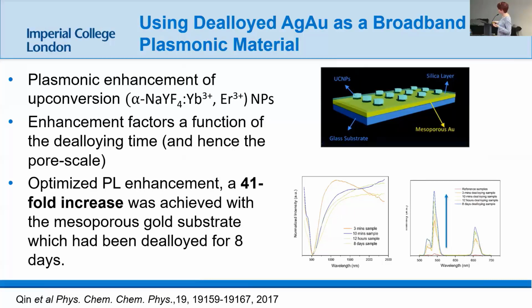This is the optical response of dealloyed gold. So normally if you see a plasmonic response, so you took a beautiful gold nanoparticle and everyone's seen kind of ruby red gold, you get a very sharp plasmonic peak because it's got a very well-defined size and surface plasmon. So with these materials, you've seen that there's a huge range of curvatures, right? And so we get this really broad band response. And that's actually really useful because what that means is if I want to couple to that plasmon peak, I've got a very wide window of wavelength that I can do that with.